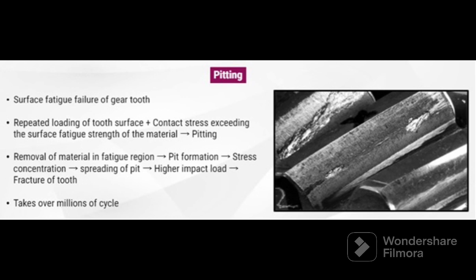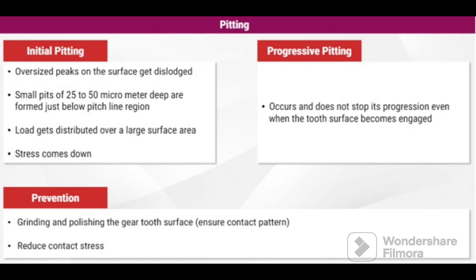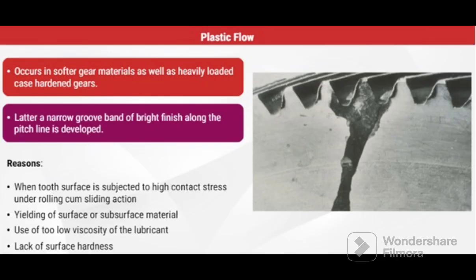There are two types of pitting, initial and progressive. Initial pitting occurs during running in period wherein oversized peaks on the surface get dislodged and small pits of 25 to 50 micrometer deep are formed just below pitch line region. Later on, the load gets distributed over a large surface area and the stress comes down which may stop the progress of pitting. Progressive pitting is a wearing phenomenon which does not stop its progression even when the tooth surface becomes engaged. We can prevent pitting by grinding and polishing the gear tooth surface, ensuring contact pattern and by reducing the contact stress.